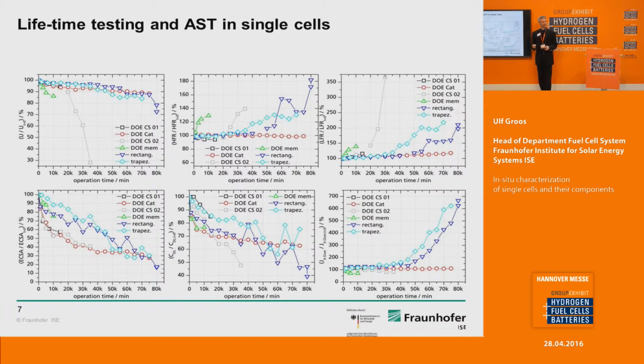This was a characterization of performance, but I'd now like to focus on characterization of degradation effects. What you see here in a lot of graphs is that we performed degradation testing, accelerated stress testing, according to the testing protocols of the Department of Energy in the US. There are different accelerated stress tests regarding the catalyst support and regarding the catalyst itself. We performed the degradation of the catalyst support two times. Then there are protocols for the membrane, and we also did some in-situ characterization with different load cycles.